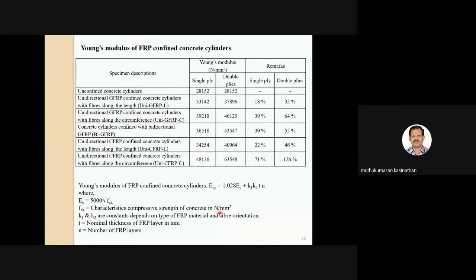And using the cylindrical samples, we have also obtained the modulus of elasticity of the concrete, Young's modulus, for various conditions. And you can see here, it is very similar to the earlier response. The modulus is also increased with the carbon fiber in the circumferential direction. It is the expected one. The improvement is 71% for single ply and 126% for double plies. So again, the Young's modulus for FRP confined cylindrical samples can be obtained using this equation.